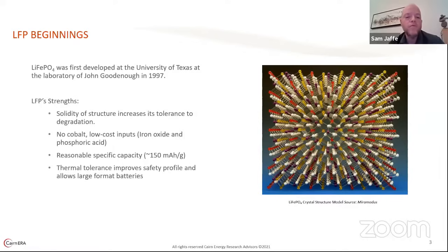It had a lot of reasons to be excited about it. If you look at the molecular structure of it in that image on the right, it is a solid, bulletproof material. It is like a big iron cage where the lithium ions can go in and out through the channels within that crystal structure, as opposed to most other cathode materials, which are essentially layers on top of each other. Think of a game of Jenga where the lithium goes into the empty spaces there. But it does have some issues too with that crystal structure, which I'll get into in the next slide.